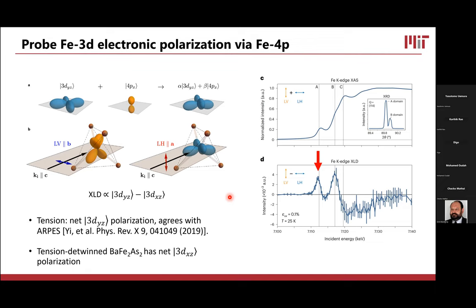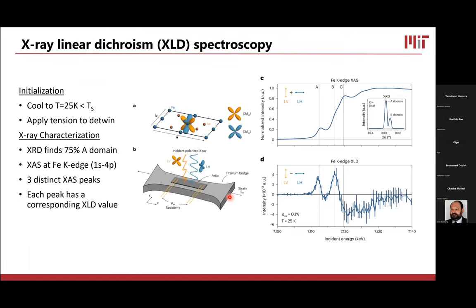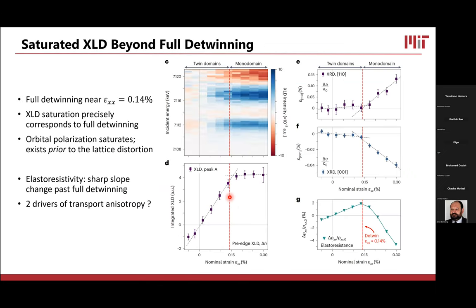I'm not particularly concerned about the origin of the orbital polarization. I was more concerned about knowing what the orbital polarization is doing, how much information you really have in addressing the question, what is driving the nematicity, right? Because, say, in the spin channel, the anisotropy information is actually available over a very, very large range of energies. That would help. And we've done that measurement in neutron scattering. We did the X-ray scattering experiment, basically looking at the detwinned sample.